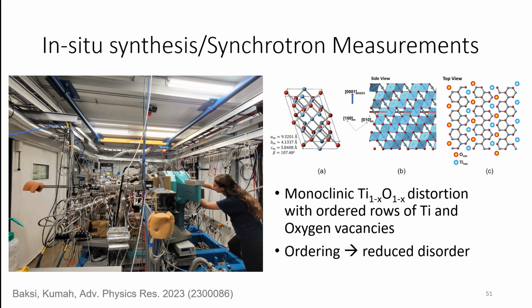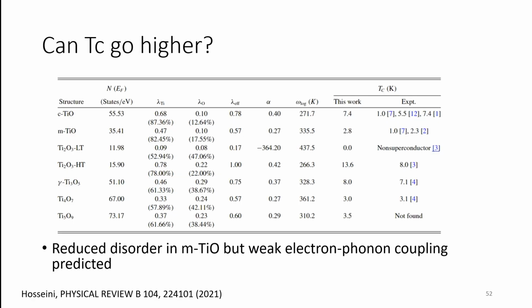So in the cubic phase, the vacancies are disordered, and we think that this order might give rise to that insulating phase in the normal state. But if you can reduce this order of the vacancies, then we think that's what leads to the metallicity in the system. But the question then was, if we have reduced this disorder in this system, why isn't TC room temperature?